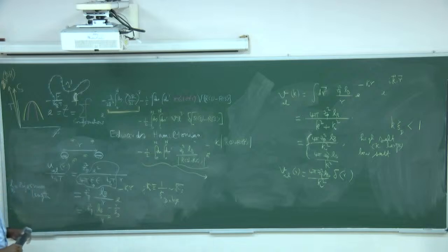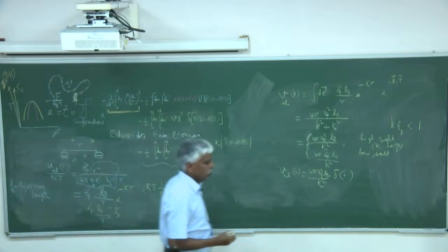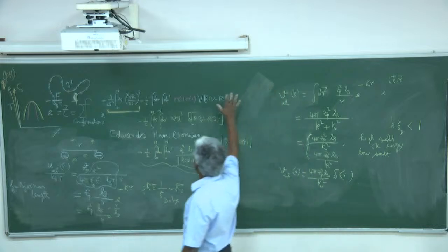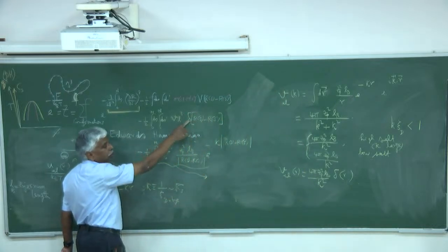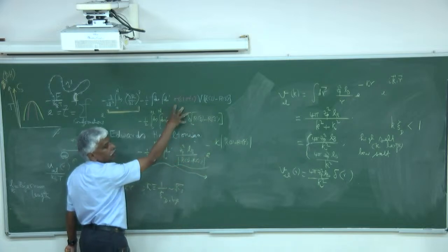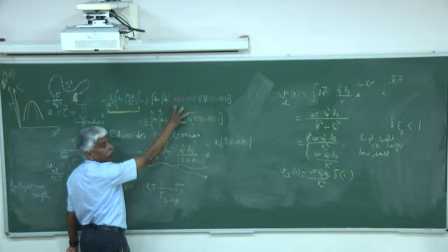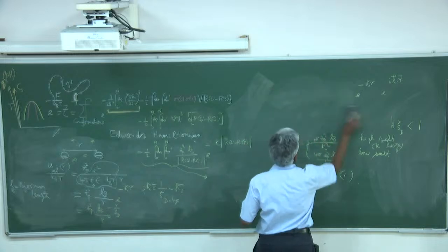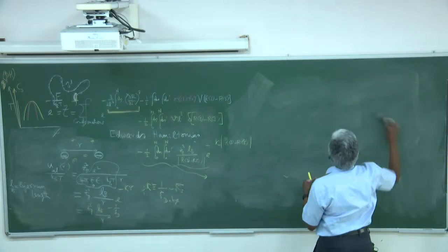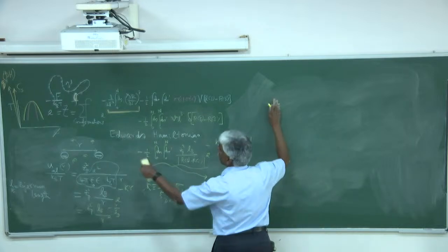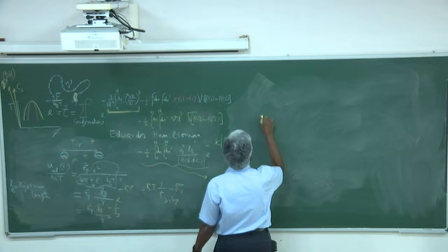My Flory theory, well, not Flory theory, the Edwards Hamiltonian becomes e to the minus 3 over 2 L square integral from 0 to n of ds (dr by ds) square, plus v plus 4 pi Lb Zp square over kappa square, times one half, double integral from 0 to n of ds ds prime delta of r of s minus r of s prime.